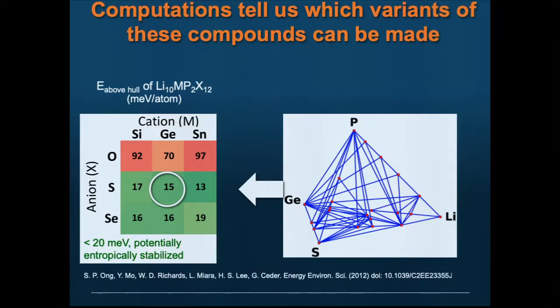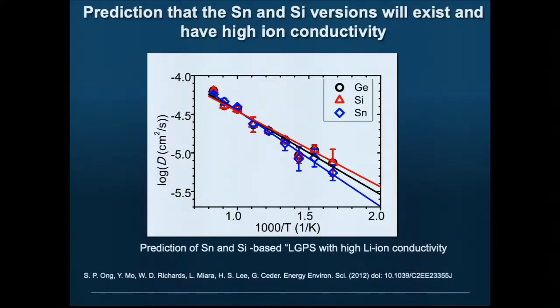And this is the energy by which it's metastable. And this is the compound that's been made. So the sulfur germanium version is metastable by about 15 millielectron volts per atom. But what you see is if you go to tin or silicon, that doesn't change dramatically. Or if you change sulfur to selenium, that doesn't change much. So in principle, these should be able to be made. You can calculate that they have similar conductivity.